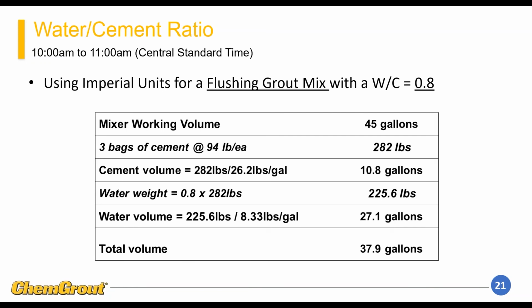So in our hollow bar grouting, we have two different types of grout mixes we're going to use. We're going to use a flushing grout while we're drilling, and then when we're done drilling, we're going to pump out all the flushing grout with a structural grout. So the flushing grout is usually a water cement ratio of 0.8, which would be 3 bags of cement to about 27 gallons of water, which would yield about 38 gallons total volume of cement slurry. And that's what we'll mix up to use for our drilling while we're drilling.